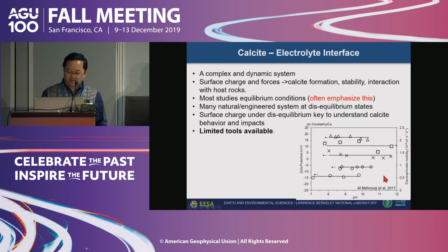And for calcite, the charge determining ions are calcium and carbonate ions. This is a nice illustration of how the zeta potential is independent of pH, but rather controlled by pCa. So there's a very strong connection between surface charge and the forces on the surface that have a strong impact on how calcite forms, and the stability of the calcite mineral, and also how that calcite interacts with host rock.